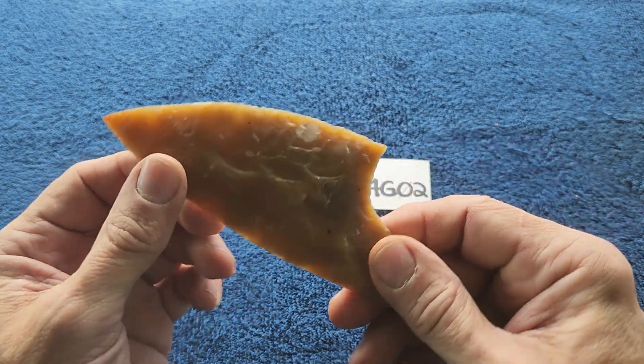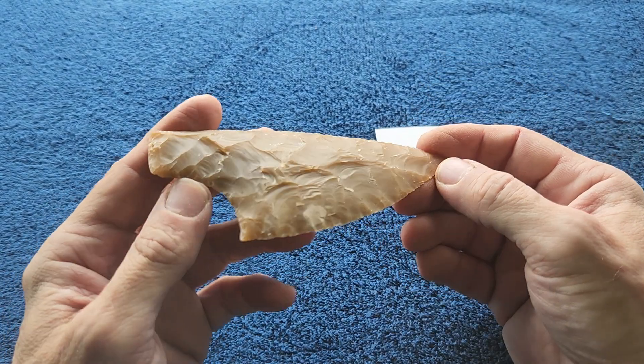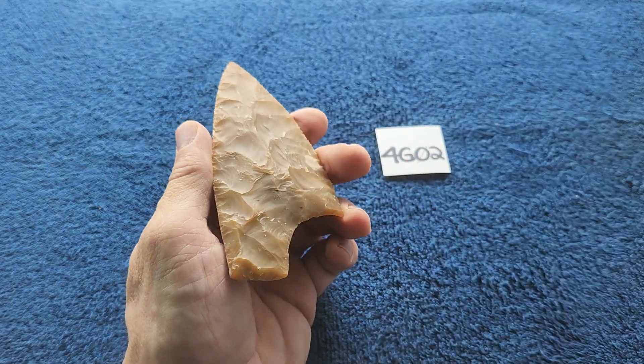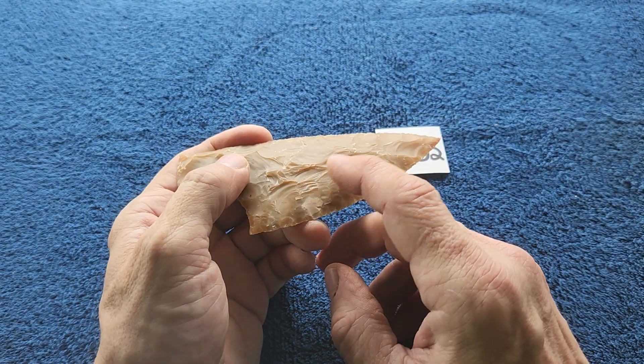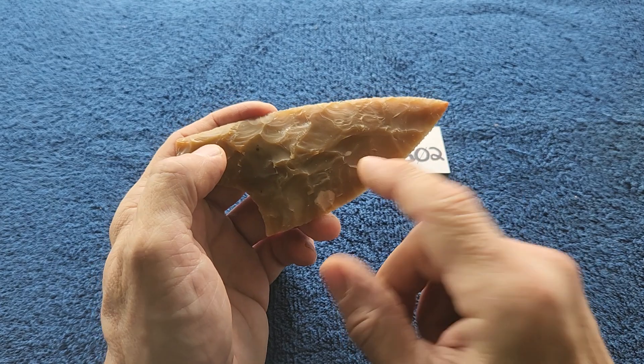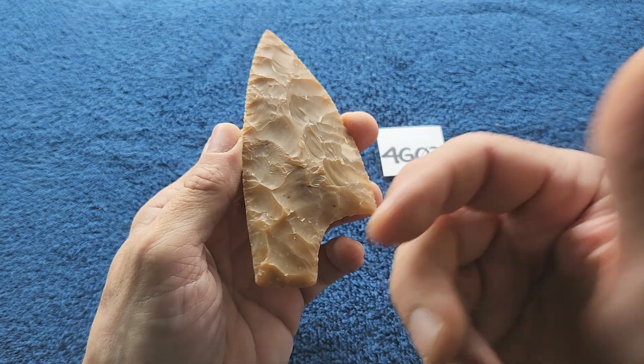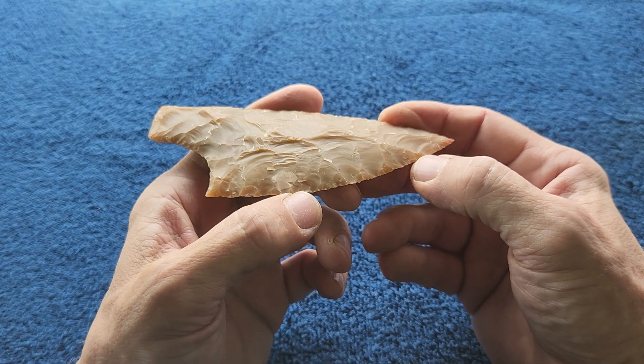Item 4g02 is a knife blade, heat-treated Georgia chert — same batch, 400 degrees. That's a little bit too high for Georgia chert because sometimes pieces will just snap in half extremely easily. From now on I'm going to stick to a range of 345 to 385 degrees on the Georgia chert — the butterscotch variety at 345 and the swirl up to 385.